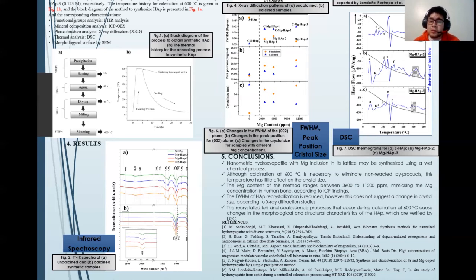mimicking the magnesium concentration in human bone, according to inductively coupled plasma findings. The FWHM of hydroxyapatite after recrystallization is reduced. However, this does not suggest a change in the crystal size, according to X-ray diffraction studies. And the recrystallization and coalescence process that occurs during calcination at 600 Celsius degrees causes changes in the morphological and structural characteristics of the hydroxyapatite, which are verified by differential scanning calorimetry.